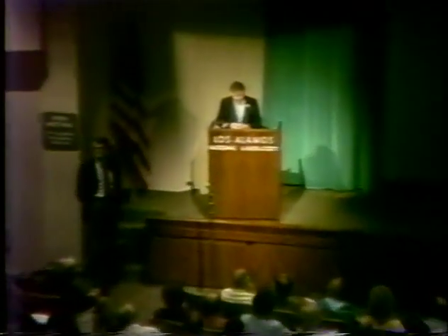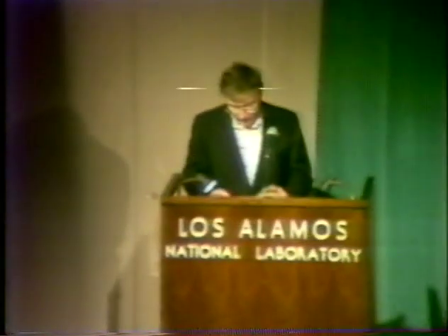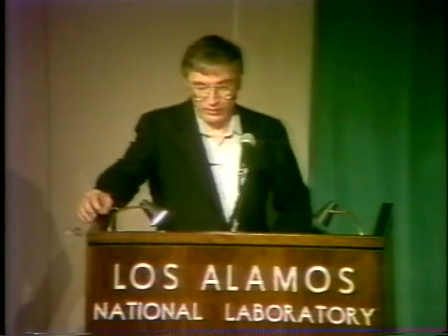Chevy Walling and Jack Simons have presented a very nice theoretical paper to a journal, which they expect to be accepted today or tomorrow, according to the reports. And in this theory, they very accurately predict the fusion rates and the energies that we should be seeing. One of the other predictions they made was that we should see helium-4. We never looked for helium-4, and we went back to the old mass spectral data for January, and sure enough, there are two very well-defined peaks at mass 4, one for the deuterium and one for helium-4, which we've substantiated.